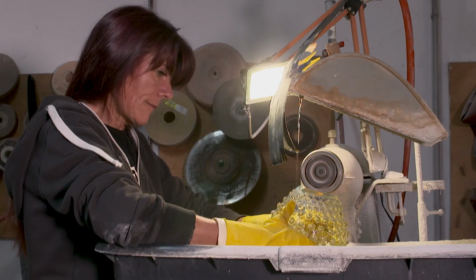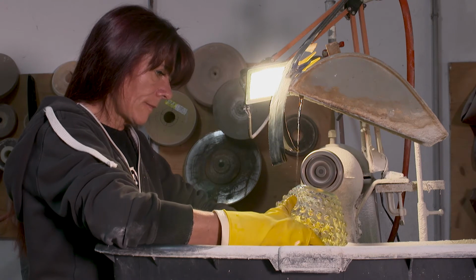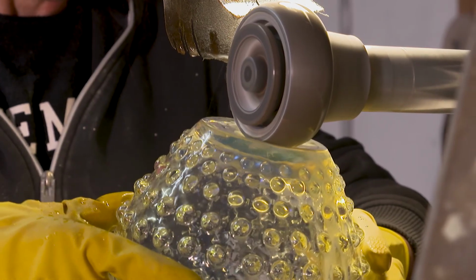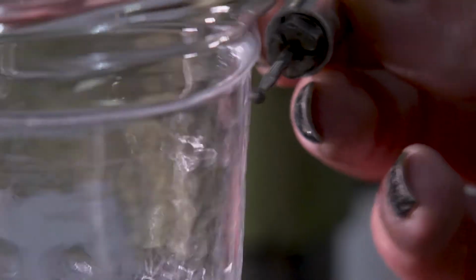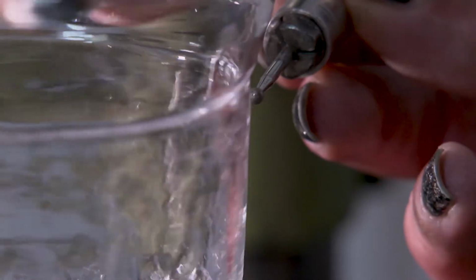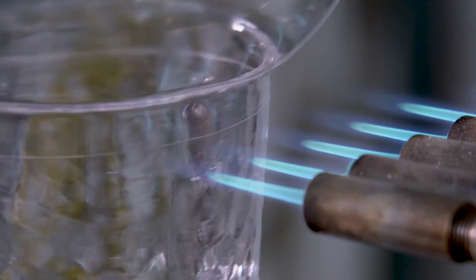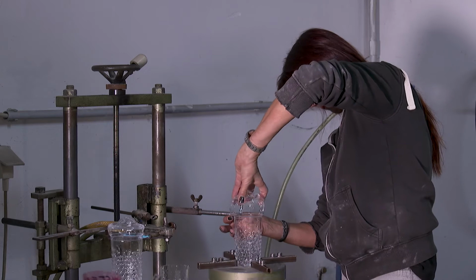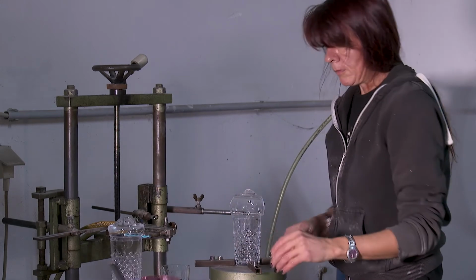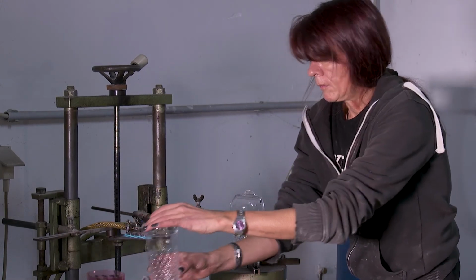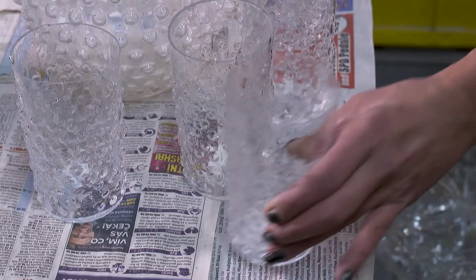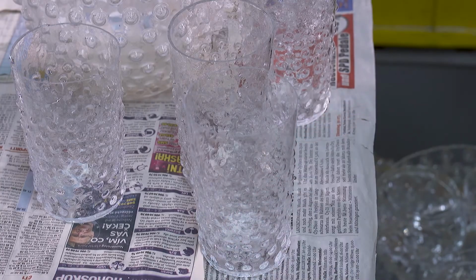Redundant glass that forms at production, so-called caps, gets removed. First, a line is drawn by a fine diamond point. Hot gas flames with about 1,400 to 1,600 degrees Celsius are responsible for surface tension. As soon as the thickness, no matter their dimension, is heated through midway, physical compressive and tensile stress is created. The cap falls off along the drawn line, the predetermined breaking point.